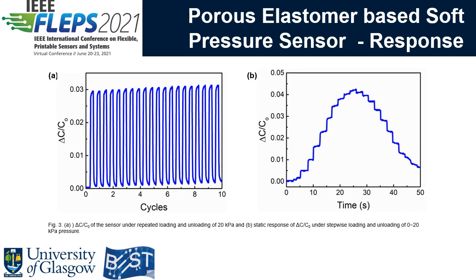The stability of the sensor was examined by cycles of loading and unloading of 20 kPa pressure. As shown in Figure 3a, the sensor demonstrated a stable change in capacitance without signs of fatigue, suggesting good durability. The slight drift in response can be handled with suitable readout electronics and requires further investigation. Figure 3b presents the sensor's capacitance changes when static pressures of 0 to 20 kPa were loaded and unloaded in a stepwise manner. The capacitance changed quickly and reversibly, indicating that the porous elastomer-based soft pressure sensor had stable response.